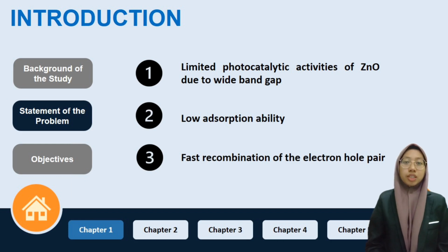Despite the potential advantages of zinc oxide, the photocatalytic activities of zinc oxide are limited by the irradiation wavelength in the UV region due to the wide band gap. And then the absorption ability of the high energy portion of UV is restricted. And the last one, the fast recombination of the electron hole pair, which decreases the photocatalytic degradation efficiency.